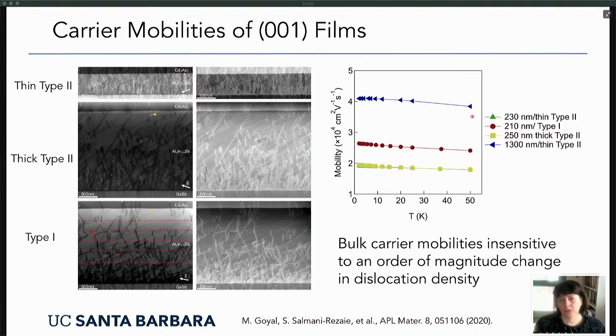So interestingly enough, and this is just data looking at mobilities for essentially these very same films, if you make the cadmium arsenide films very, very thin, we get mobilities here of about 40,000, which is quite good. And then interestingly enough, even if you have these very heavily dislocated thin buffer layers, where we'll have lots of dislocations in the cadmium arsenide, and a case where we have a thicker buffer layer with few dislocations in the cadmium arsenide, the mobilities are actually not that different. But if you make them thicker, they actually get better. So there's a challenge with making thinner films. But the dislocations are pretty high.